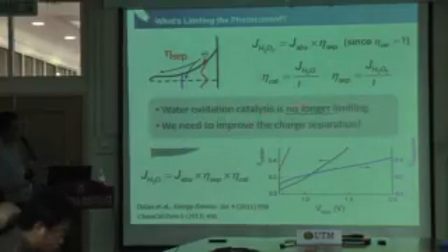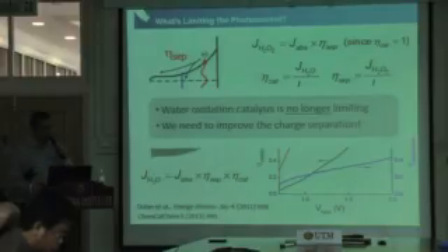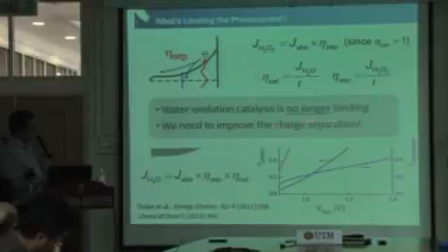But the problem now is in the carrier separation, which is the blue curve over here. It doesn't change if you put cobalt phosphate, because this is the bulk property. And it remains lower than 0.4, which means more than 60% of the carriers that we generated, that we absorbed, recombine before they even reach the interfaces, right? So the message is that water oxidation catalysis is actually no longer a problem. The problem is the charge separation. If we improve this, we're going to improve the performance of bismuth vanadate further.